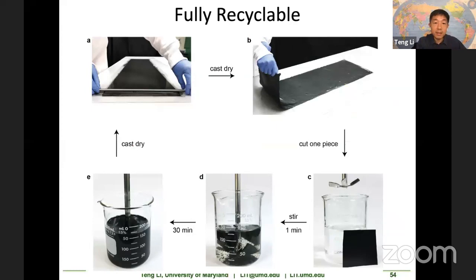It is fully recyclable. After you make this film, you can put it back in water and use mechanical stirring. And you can go back to this slurry and use this slurry to concentrate to go through this cycle again. Of course, this water stability is a double-edged sword.